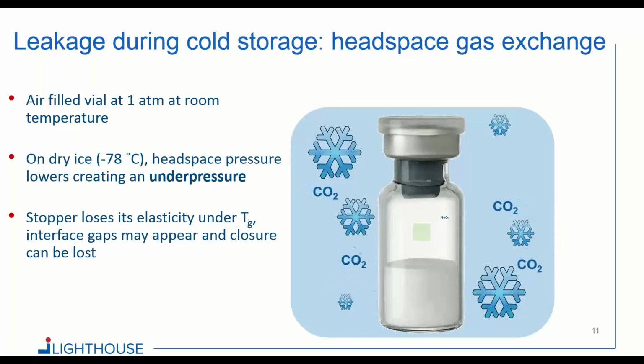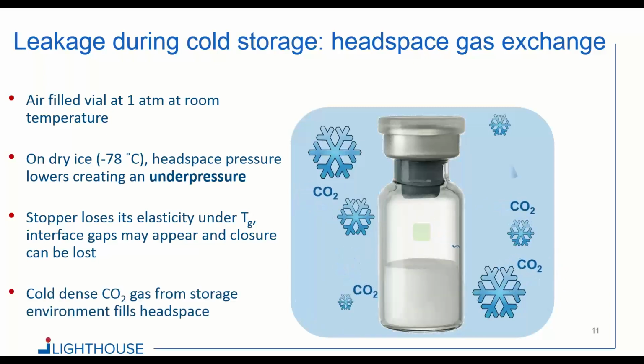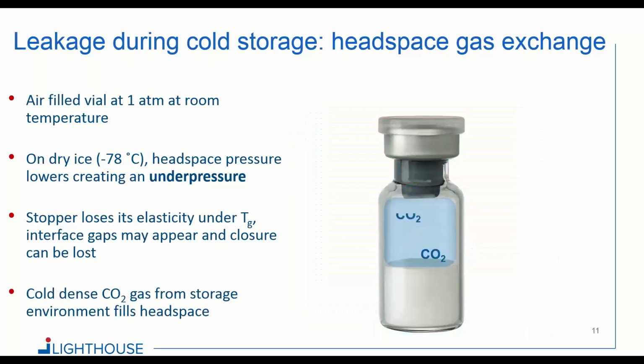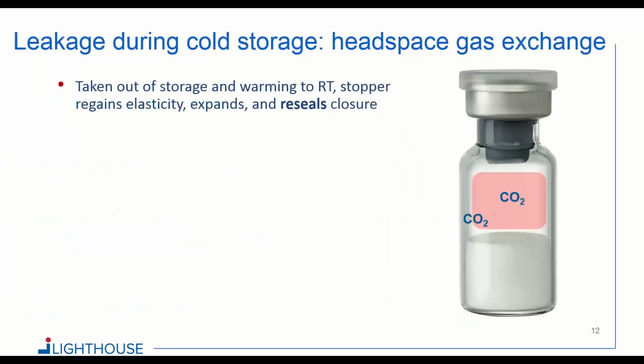Let's say that the stopper loses its elasticity under its glass transition temperature, which for most rubbers is in between -55 to -65 or -70. And that because of the shrinkage that also happens, interface gaps appear and the closure is lost. So what happens then? Well, now what you have is a vial that starts to ingress this cold, dense CO2 gas from the storage environment. It happens rather quickly because of this underpressure, and so you end up with a vial that fills up with CO2. So it was fine outside of deep cold storage. Inside deep cold storage, it's actually open and ingresses the cold gas from the storage environment.